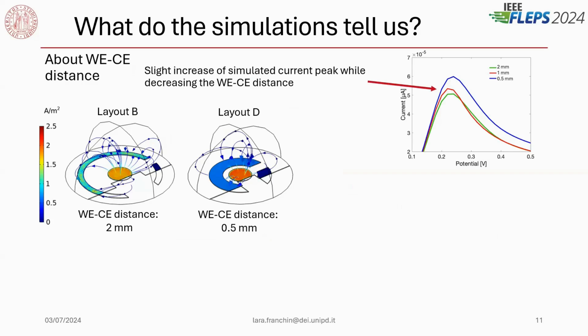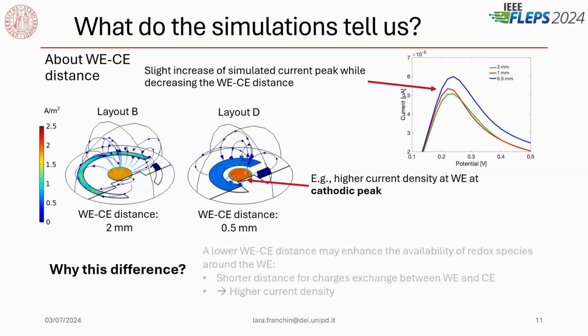And about the different distances, we can see that while decreasing the distance between the working and counter electrode, we can see a higher peak. And this is even more visible by looking at the current density at the working electrode. In fact, for the closest configuration, it's higher than the other ones. And why this difference? Well, a lower working and counter distance may actually enhance the presence and availability of redox species at the interface, so around the working electrode, and so we have a shorter distance for the exchange of charges between these two electrodes, which increases the current density.